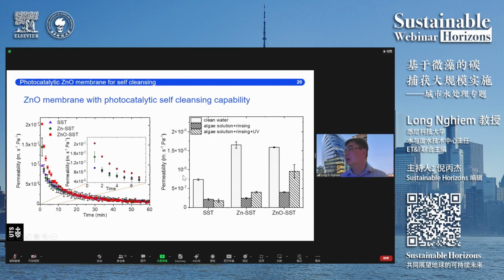After coating, we filter the microalgae solution, achieve 90% recovery, and then we do the self-cleansing. We can see that with the zinc oxide coating, after we irradiate it with UV, the flux recovery was significantly higher than when we only rinse the membrane without UV irradiation, and we can recover about 60% of the initial flux. Now, 60% of the initial flux is not very high, and this is only the beginning of our work. Nevertheless, we have effectively shown that there is some self-cleansing property. Now, we do need to bring that 60% flux recovery to 100% flux recovery, and it is ongoing.